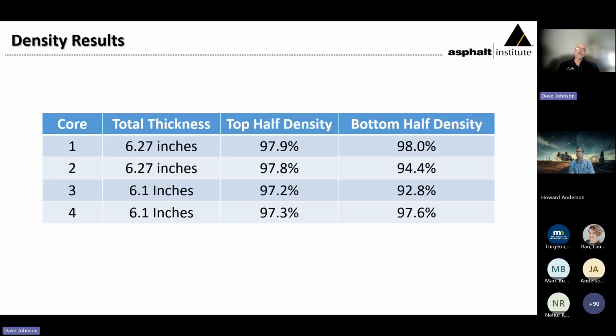What kind of densities did they get? Well, Utah is a percent within limits state, and they did apply PWL calculations to the cores, but only the top half of those cores. And so they popped a total of 4 cores and cut those cores in half, and then measured the density both top and bottom. And the densities in the top half were very, very consistent. We see the ranges between 97.2 up to 97.9.